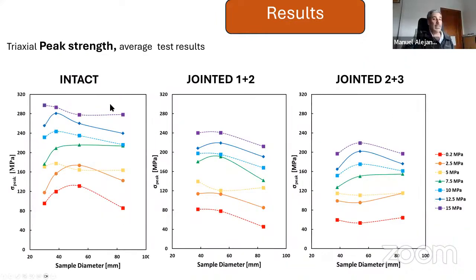So here we can see the different average results for each sample diameter and confining pressure, for intact, for jointed 1+2 and 2+3, sorry. As we can see, when we increase the confining pressure, we can also see that the peak strength increases.